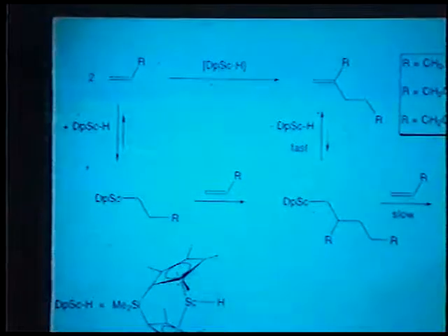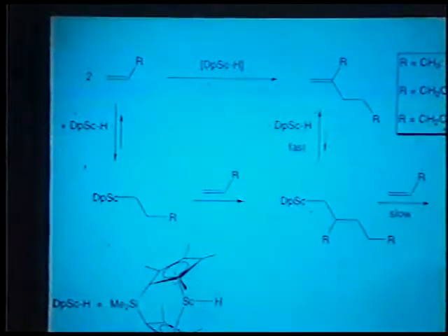This is entirely expected if one simply argues sterically. The olefin insertion into the scandium hydride bond would be expected to produce a less crowded terminal alkyl. And all this may go on many times before a second olefin insertion occurs. If that olefin insertion does occur, now we have a beta-beta disubstituted carbon here. The transition state electronically wants to be carbocation-like, or ideally suited for beta hydrogen elimination at that stage. And of course, second insertion is disfavored relative to very fast beta hydrogen elimination here. And these kinds of selectivities, I think, reflect that very strong preference for beta hydrogen elimination in these systems.